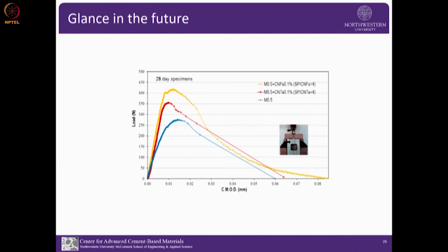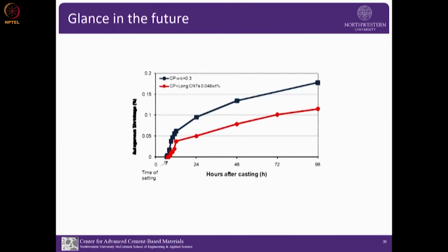Now we know that with carbon nanotube at 0.1%, they are well dispersed, and we asked, why is it working so well with such a small amount? At that time we had our MIP, but Northwestern was saying, no, we cannot use it because one of the students had spilled some mercury. So we couldn't measure it. So we asked, what other property can be substantially different because of a change in nanopores? So we measured autogenous shrinkage, and we found a substantial difference.